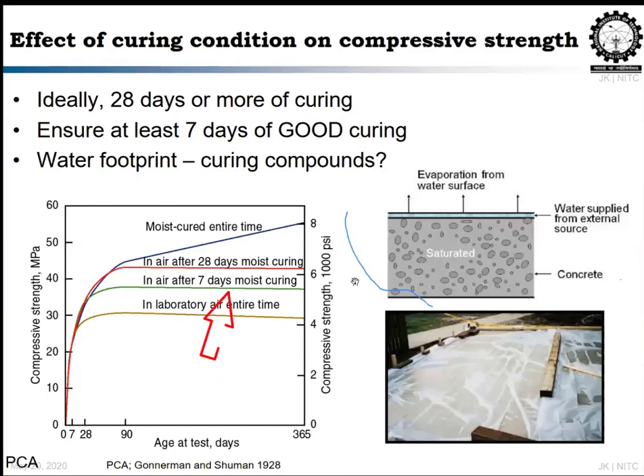The second case, which is green color, is 7-day cured in moist, like how we do, or ponding, and then it is exposed to air for 1 year. And the third case, which is in red color, cured for 28 days and exposed to air for 1 year. And the fourth case, which is the dark blue line, is moist cured throughout the entire time of the exposure. So here, if you see the case where it is not properly cured, it means air cured, it is giving only less than 30 MPa on 90 days, which looks similar on the 28th day. There is not much difference.